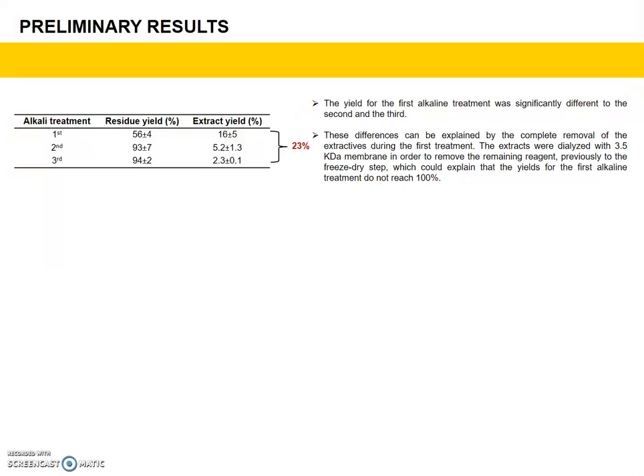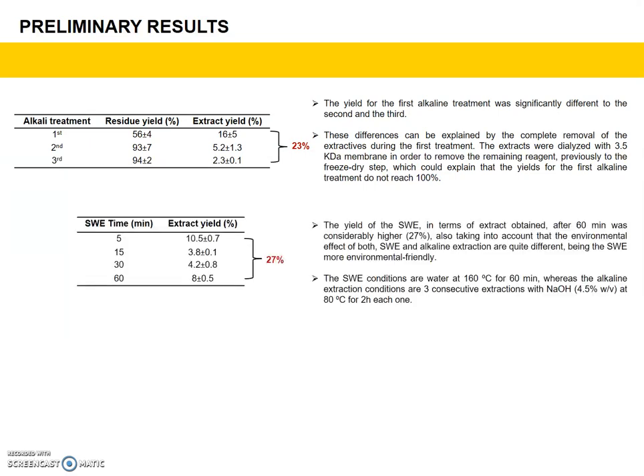The extracts were dialyzed in order to remove the remaining reagent prior to freeze-drying, which could explain why the yields for the first alkali treatment do not reach 100%. On the other hand, the yield of the subcritical water extraction in terms of extract obtained after 60 minutes was considerably higher, also taking into account that the environmental effect of both extraction methods is quite different, the subcritical water extraction being more environmentally friendly.